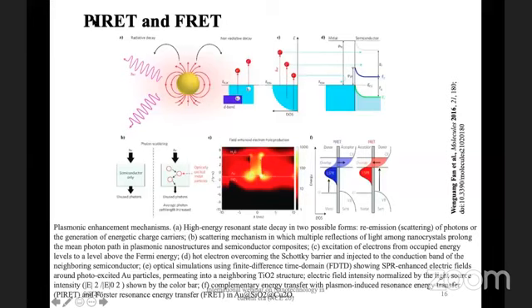Now here we have two processes. One is the plasmon induced resonance energy transfer and the other one is Förster resonance energy transfer. So we have a nanoparticle, we have a light shining onto it, and then it excites the surface plasmon. Two things can happen. It can scatter back the light or emit the light, or it can excite an electron into what we call a hot electron, if we have this nanoparticle embedded into a semiconductor.